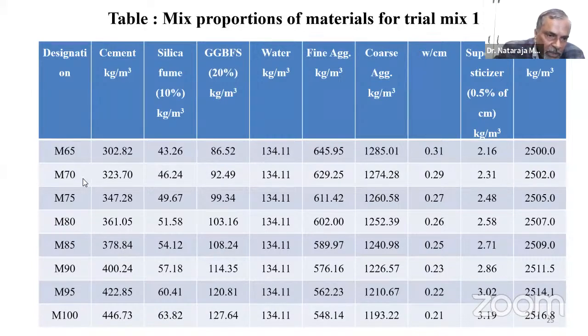And also kindly see the cement. The cement is 302.82 going up to 450. Kindly see 446 means I have ensured the requirement the code is telling. So the cement content should not be more than 450 kg, but not the cementitious system. Cementitious system means cement plus silica fume plus GGBFS. So when you add all these things, probably it might cross 450 suggested by IS 456. But mind you, IS 456 is not the code meant for high strength concrete. It is only for the standard concrete.